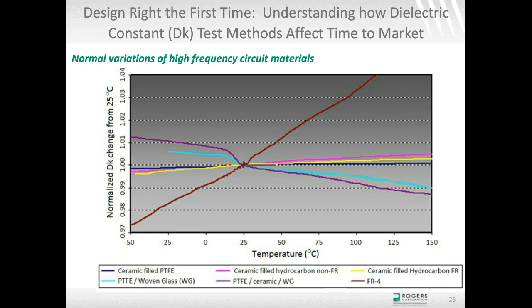And then the dark blue curve that's hovering really close to the 1.0 perfect line, that's actually our RO3003 materials, and those materials have a TCDK of 3 parts per million per degree C, which is just about perfect, perfect being zero. Anyway, the dark blue line, you can see from left to right, going from minus 50 degrees C up to plus 150 degrees C, there's very little variation in that, and that is really due to using the right combinations of fillers and different magical things that we throw into the laminate to control different properties. In this case, we're controlling TCDK very well.